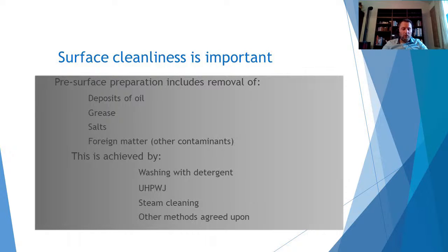Surface cleanliness is important. Surface to be coated requires some pre-cleaning, since the steel that comes from the workshops surely has traces and presence of potential contaminant. Inspecting for contamination, including heavy deposits of grease, soil, dirt, dust, or cement spatter, is an important component of the coating process. Types of contamination could be rust, chloride contamination, most prevalent in marine environment, salt refining industry, and coal mining. We can also have acidic contamination, alkali contamination, and organic contamination.